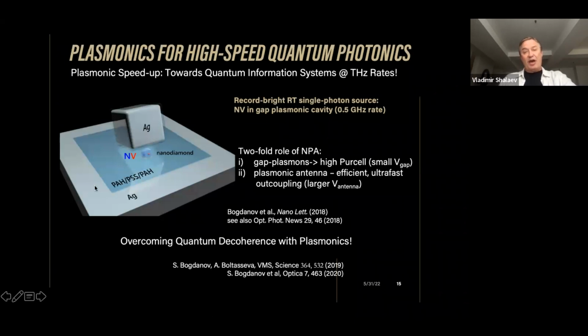So in this case, you have epitaxial silver, and silver is an exceptionally good plasmonic material, and a single crystal silver cube. And if you place in between the cube and the epitaxial film a quantum emitter, like in this case a nanodiamond with a single nitrogen vacancy, then this spontaneous emission would be enhanced through this gap plasmon.